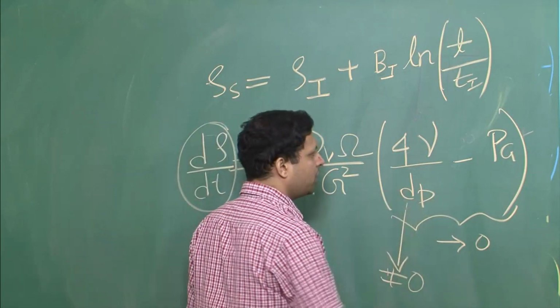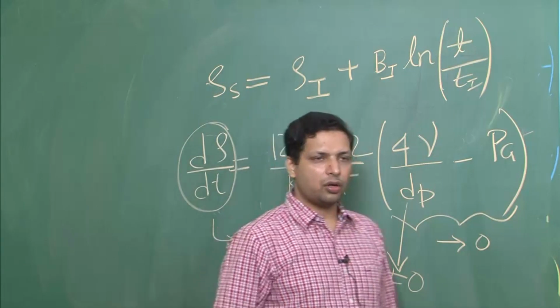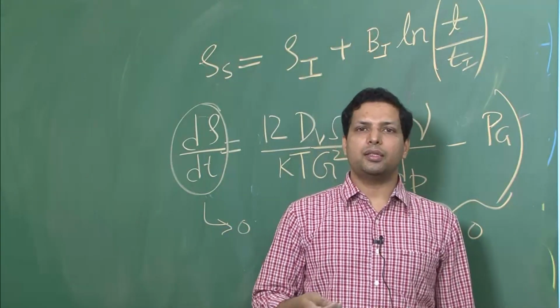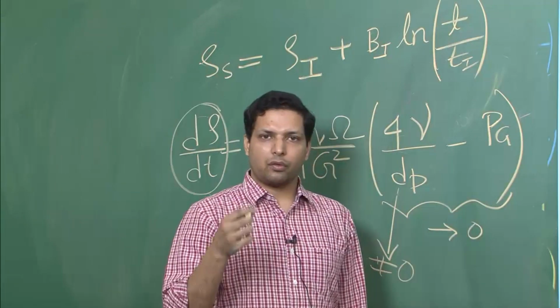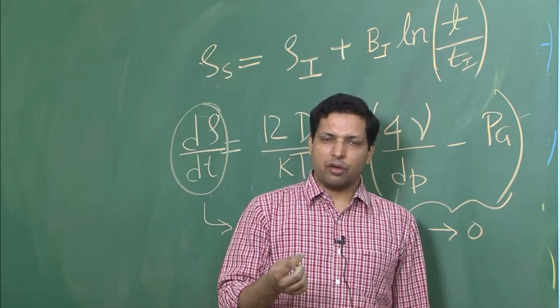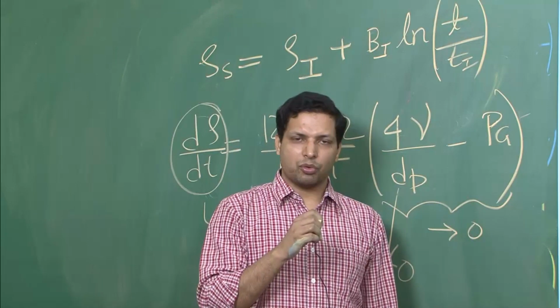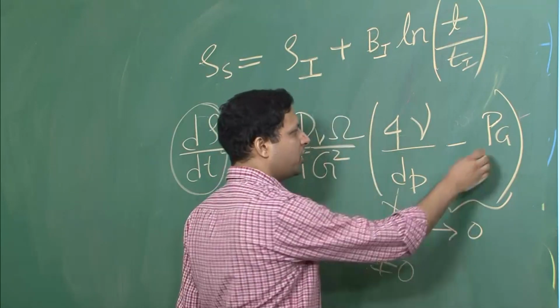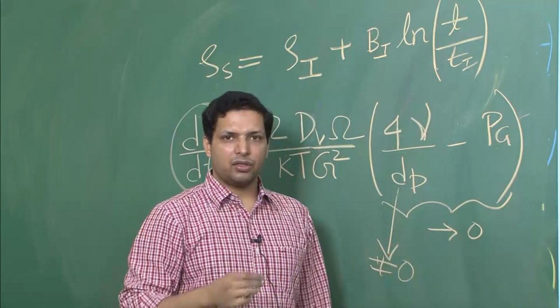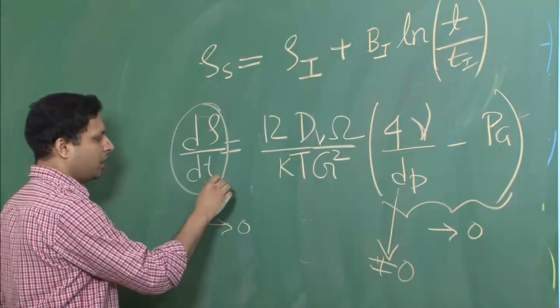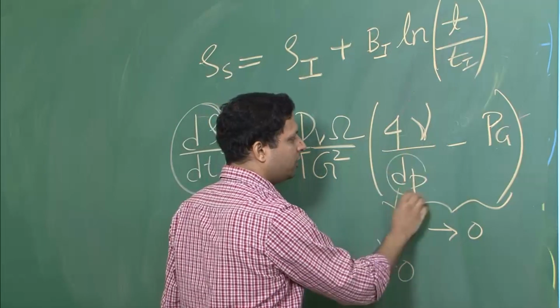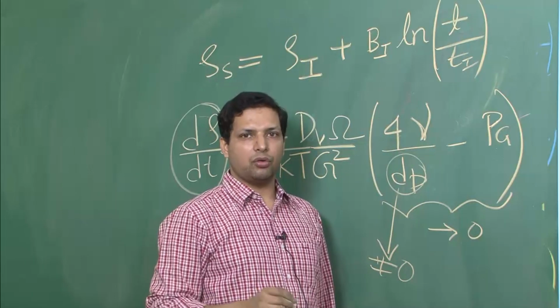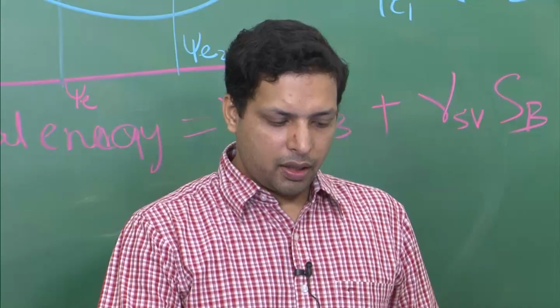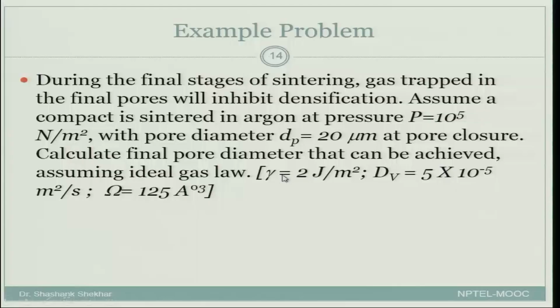So that is what can happen, or actually I should not say may happen, it does happen when you are sintering in some atmosphere, because there is some gas that you have used, and that gas gets trapped inside the pores, and because of that there is a pressure. The pressure and the surface energy term balance each other, and therefore your densification may come to 0 even before the pore size dP comes down to 0. There is an example problem you should try, and you can discuss it with the TAs and try to solve it on your own.